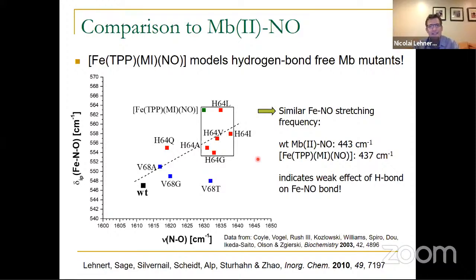And what you find is that the model complex is very similar to myoglobin mutants where the distal histidine has been removed. You know that in myoglobin, we have a hydrogen bond to the diatomic bound to the iron center. And if you remove that histidine responsible for this hydrogen bond, you essentially have something very similar to the model complex, which of course does not have this hydrogen bonding either. And that's what's indicated here in this vibrational correlation plot, where we're looking at the NO stretching frequency versus the energy of this bending mode.